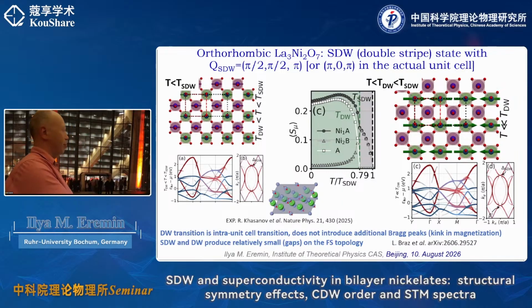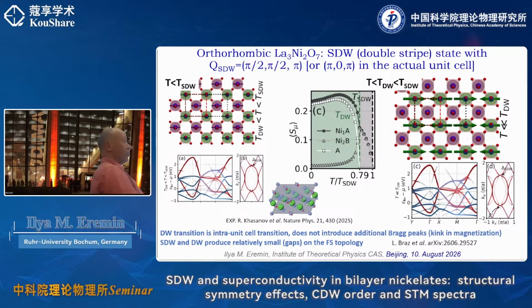And the consequence of this intra-unit cell charge density wave order is that it suppresses the magnetization on one of the sublattices. So you want to move towards a spinless stripe, double stripe. Of course, below a certain temperature, where exactly this temperature is depends on the microscopic details, it can shift as a position of the crystal field splitting. But what is essential is that at a certain temperature, your magnetization will split. The magnetization of one sublattice starts to increase even faster, whereas the magnetization on the other sublattice starts to decrease. So you start to suppress it to form this spinless double stripe. And in addition, you will have a formation of the charge order, which appears here.